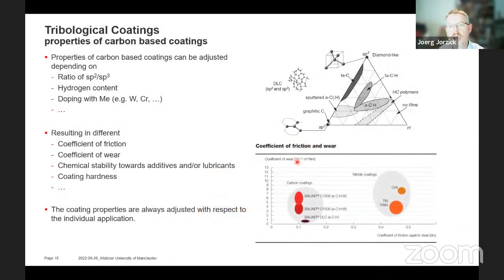However, as I said in the beginning, we try to tailor the coating with respect to the customer application. That can easily be done by playing with this ratio of sp2 and sp3 to, for example, influence the hardness or coefficient of friction, or we can add different doping elements so that we can impact properties like coefficient of friction or wear coefficient, and also have an impact on the stability, chemical stability towards additives.